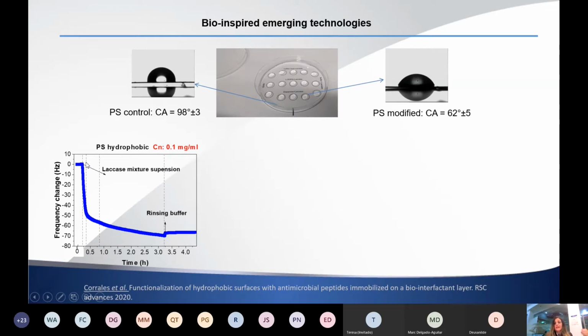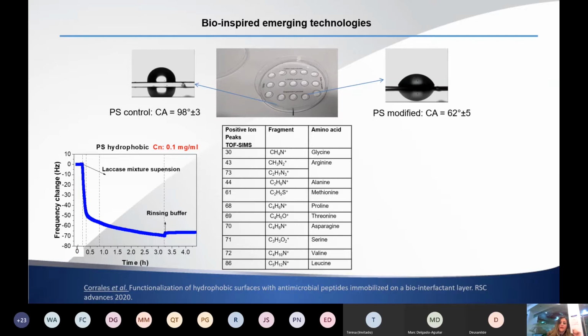This enzyme forms a film that is irreversibly adsorbed on hydrophobic surfaces in 1 minute. And it forms monolayers. What it means, a monolayer of a protein, is that I get one protein ball of 5 nanometers and I cannot form thick layers. It will get a 5 nanometer layer on hydrophobic surfaces. And then, of course, we tested if the enzyme was on the surface with techniques such as QCM.